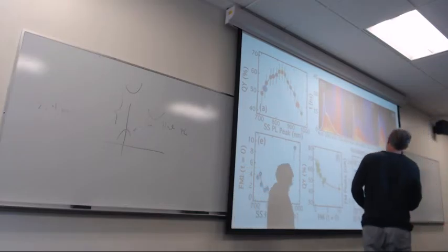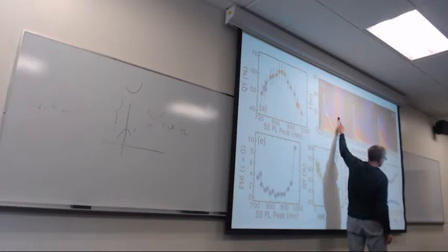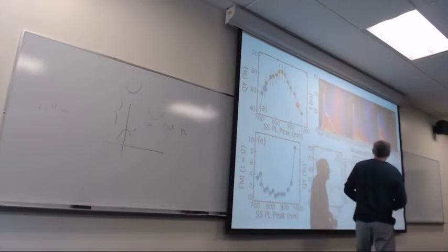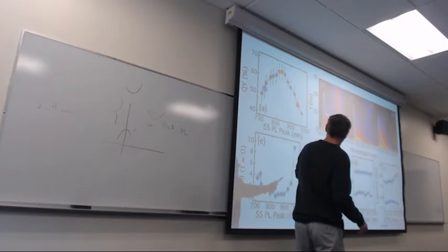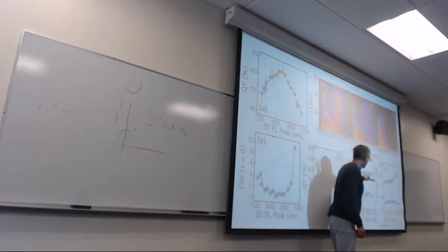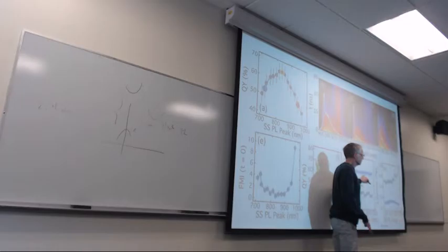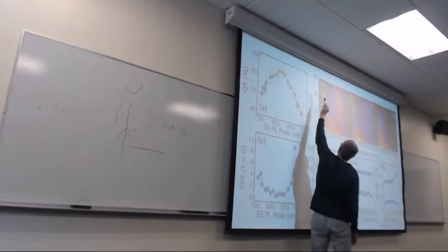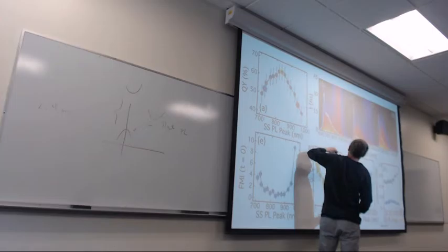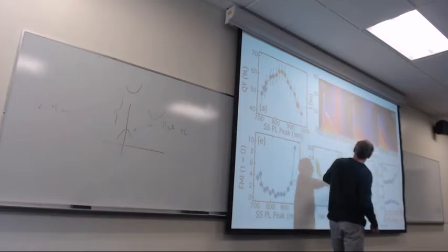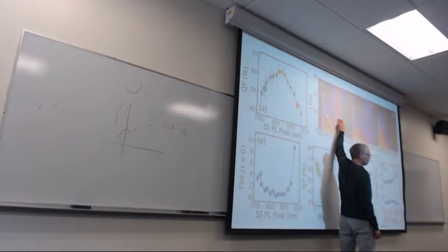This is the bulk emission right here, or the steady state PL quantum confined emission, the red band gap. This is the band gap. This other one is gone after about a nanosecond, completely gone. It's completely out of the picture. Look at the time scale here, 0 to 45 nanoseconds. So all this happens really fast, before your typical red, slow, indirect radiative recombination kicks in.